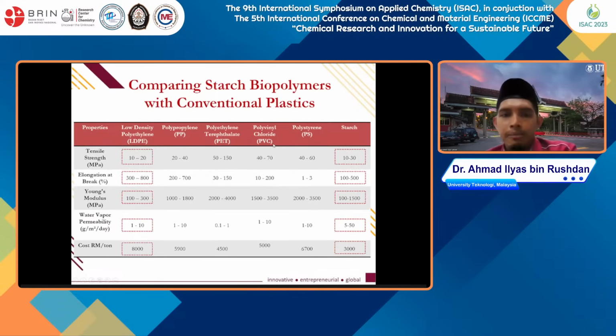Comparing the starch biopolymer with conventional plastic, this one is starch and this one is LDPE. If you look at the tensile mechanical properties, it's equivalent to 10 to 30, while the tensile strength for LDPE is 10 to 20.